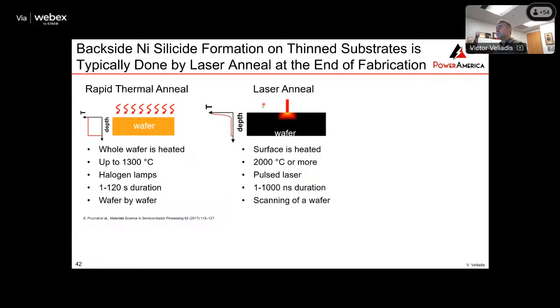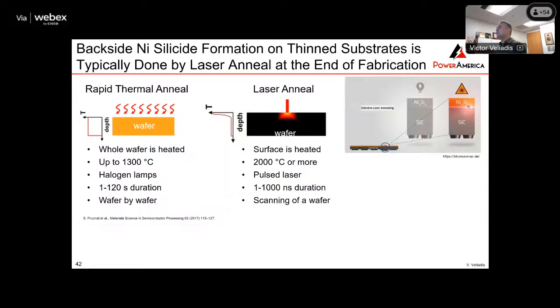If you do the laser anneal, then you're using a laser to scan the whole surface of the wafer. You go to 2,000 degrees or more, pulse lasers are used. It's a very fast process, and you scan the whole wafer. And you can see the advantage of the laser anneal that you see right here. You're only heating up the area where you're creating the silicide. So this area of the wafer is heated up. The rest of the wafer stays at lower temperature. And actually, you do it step by step as you scan across the wafer to do the silicide. The other side of the wafer stays below 100 degrees, even though this localized area gets about 2,000 degrees to form the silicide.